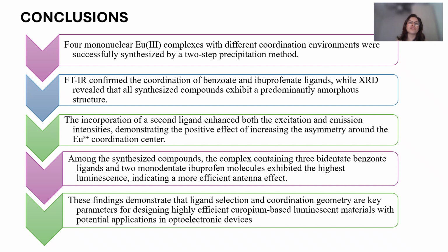The incorporation of a second ligand enhanced both excitation and emission intensities, confirming that increasing the asymmetry around the europium coordination center improves the antenna effect. Also, among the synthesized compounds, the mixed ligand complex containing 3 benzoate ligands and 2 ibuprofen molecules exhibited the highest luminescent intensity. These findings demonstrate that ligand selection and coordination geometry are key parameters for designing highly efficient europium-based luminescent materials with potential